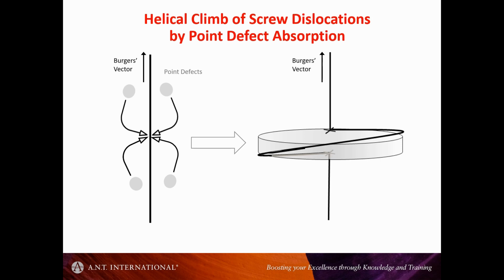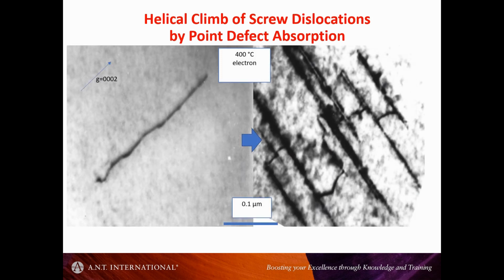The interesting thing about C-component loops in zirconium alloys is not only are they barriers to slip, but they have an effect on the dislocations directly, because the C+A dislocations I mentioned earlier will attract vacancies. What you tend to get is vacancies agglomerate on these dislocations and climb helically. If you look at a before and an after, if you have a screw C+A dislocation and then you irradiate it, you get this helical climb. We're seeing the helices edge on here. Basically that locks up this dislocation. That's a very severe hardening effect, because that dislocation is not going to go anywhere.